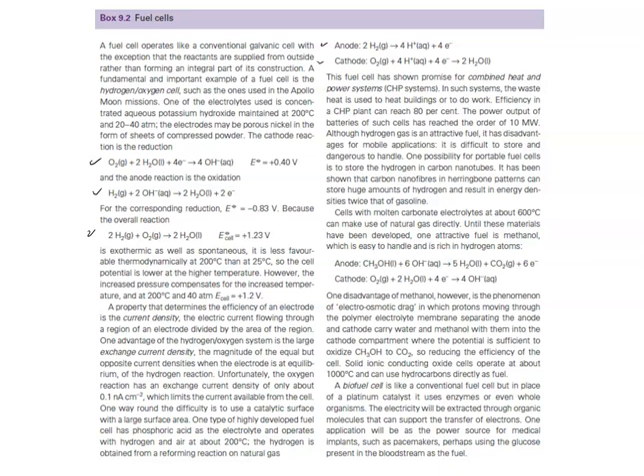One disadvantage of methanol, however, is the phenomenon of electroosmotic drag, in which protons moving through the polymer electrolyte membrane separating the anode and cathode carry water and methanol with them into the cathode compartment, where the potential is sufficient to oxidize the methanol to CO2, so reducing the efficiency of the cell. Solid ionic conducting oxide cells operate at about 1,000 degrees Celsius and can use hydrocarbons directly as fuel.